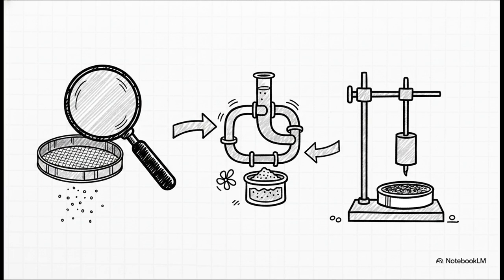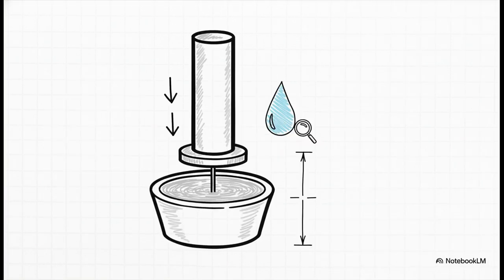But before we can even test setting times, we absolutely have to find the standard consistency, which is denoted as P, using a very specialized device called the Vicat apparatus. So the crucial point here is just how insanely exact this consistency test really is. The Vicat apparatus uses a 50mm high, 10mm diameter plunger. They carefully add water to the cement until this plunger penetrates exactly 33 to 35 millimeters from the top of a 40mm mold. Once we hit that exact microscopic dimension, boom, we've found our standard consistency, P. And this single value completely dictates the exact water ratio used for all our subsequent lab tests.